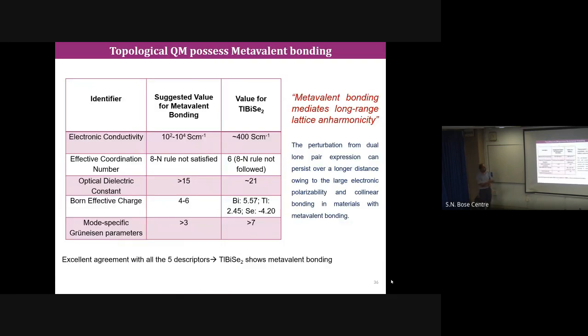So then these are the descriptors for metavalent bonding. Electronic conductivity is moderate, 400 Siemens per centimeter. Effective coordination is much lower than 18. Optical dielectric constant is above 15. Born effective charge is also anomalous, and the mode specific Grüneisen parameter is 7, much above the descriptor. So metavalent bonding mediated lattice softening we observe, and that bonding, we believe, is very unique to this class of quantum material. So this is a strong topological insulator.